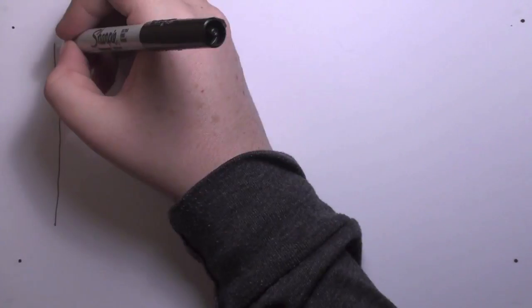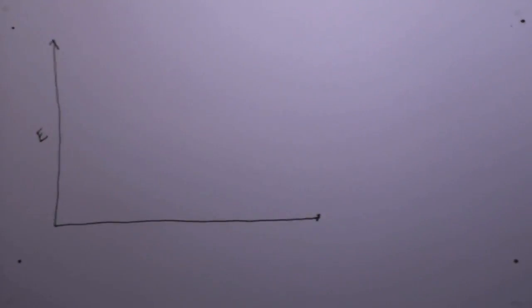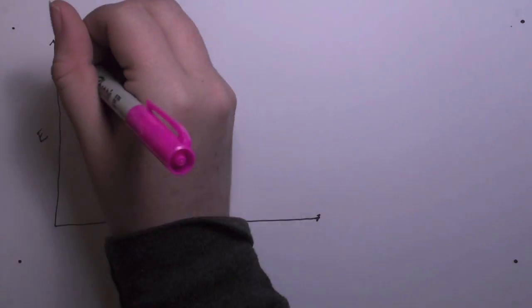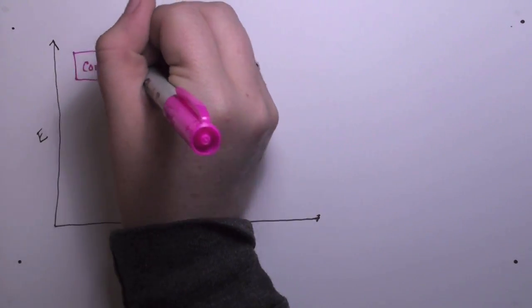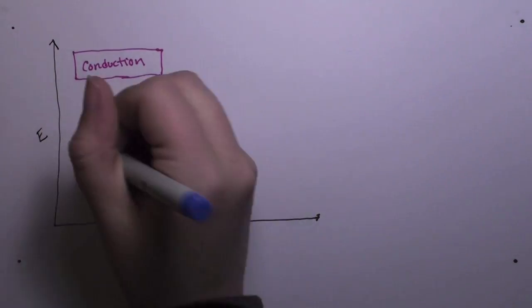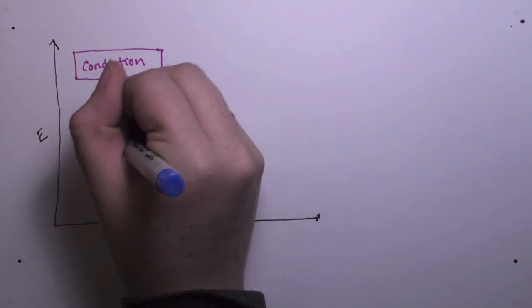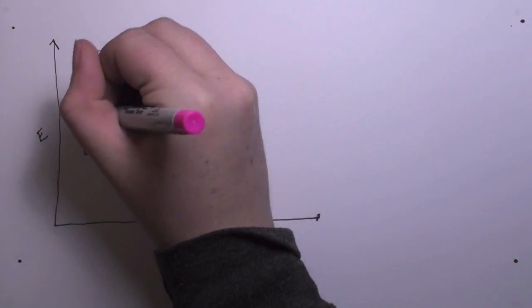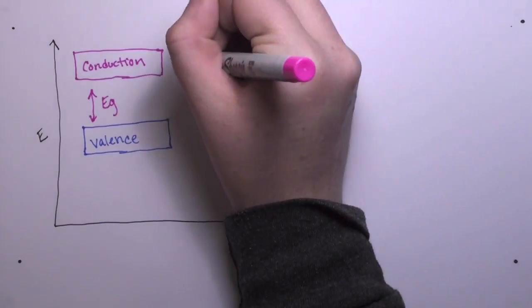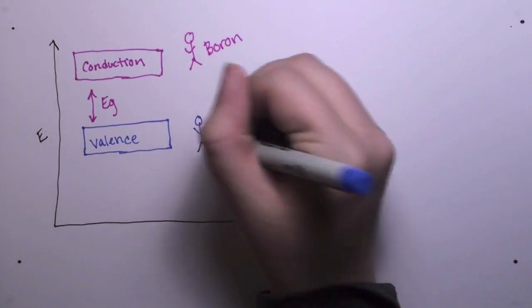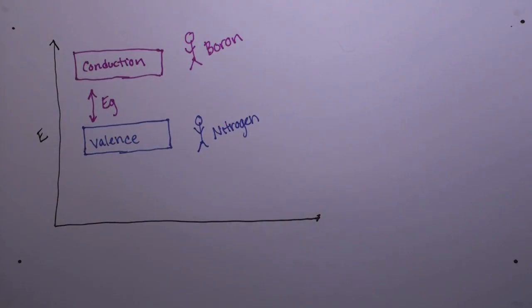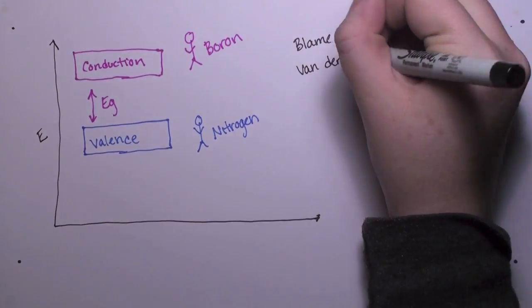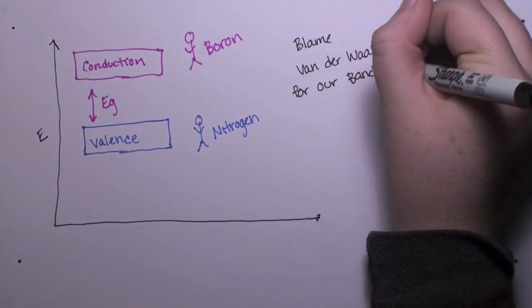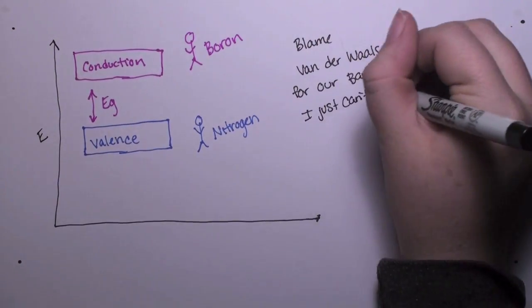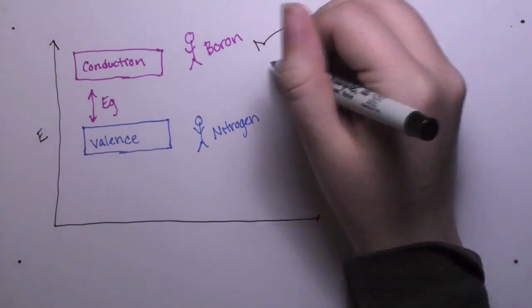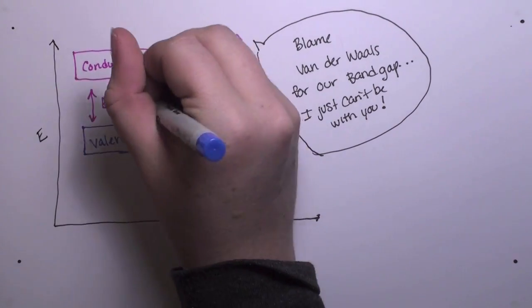Boron-nitrogen nanotubes are similar to carbon-carbon nanotubes in that they are also held together strongly with covalent bonds. However, the sheets of the nanostructures are only held together by weak van der Waals forces. This creates such a large band gap that the energy needed to overcome it causes the boron-nitrogen nanotubes to act as an insulator as opposed to the carbon-carbon metallic nature. The boron-nitrogen nanotubes act as an insulator due to the presence of a band gap of 5.5 electron volts. These will always be insulators, meaning that the energy required to overcome the band gap is independent of the nanotube's chirality.